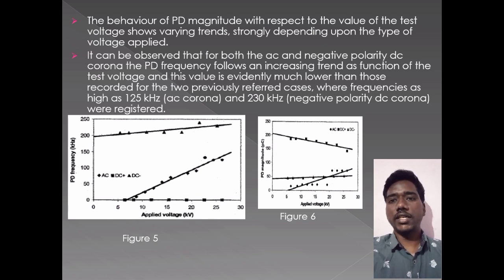The lowest CIV was detected with the application of negative polarity DC voltage, followed by positive polarity DC voltage and AC voltage respectively. From figure 6, it can be observed that for both AC and negative polarity DC corona, the PD frequency follows an increasing trend as a function of test voltage. On the contrary, the PD frequency registered for positive polarity DC corona remains constant at a repetition rate of 60 Hz. Based on the results obtained from this simplistic approach, one would expect the influence of negative polarity DC corona to be the strongest among the three cases considered.